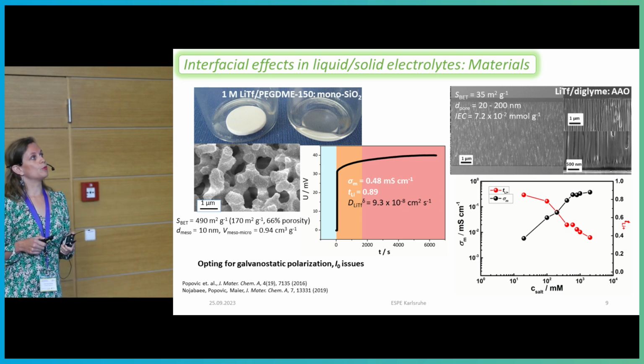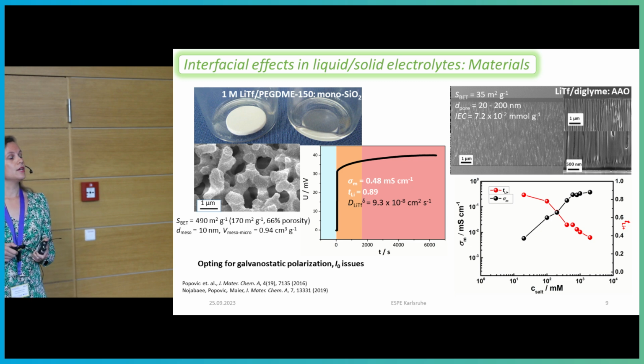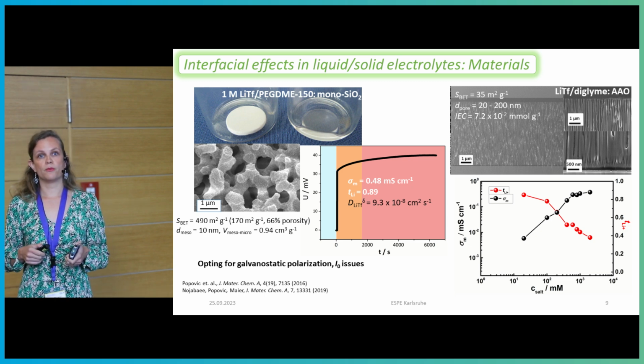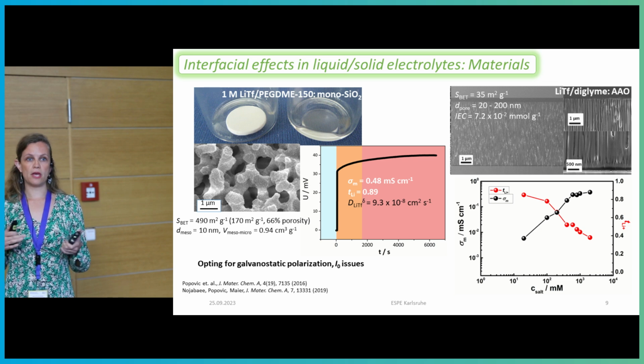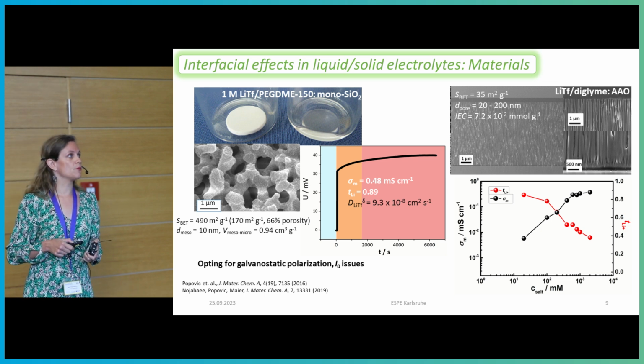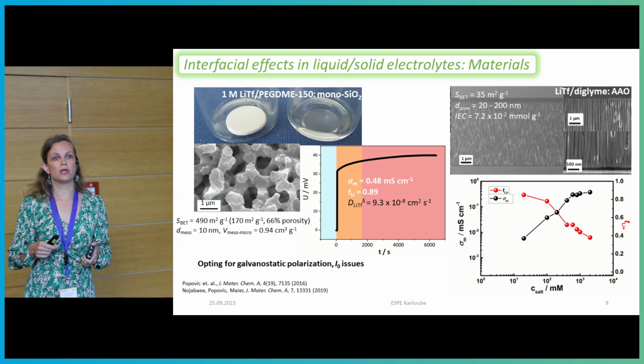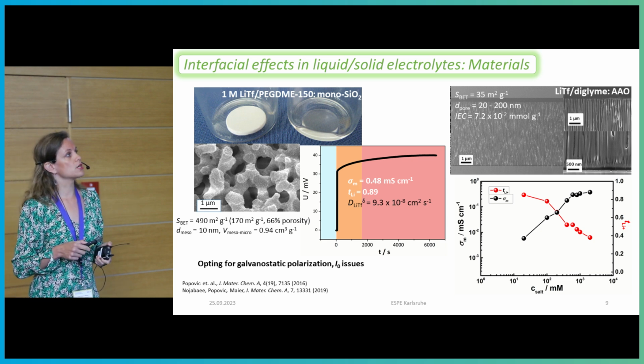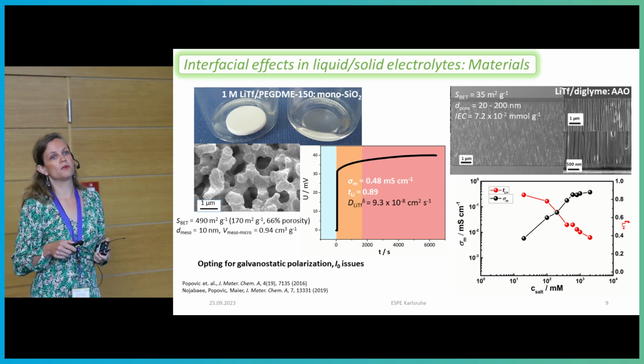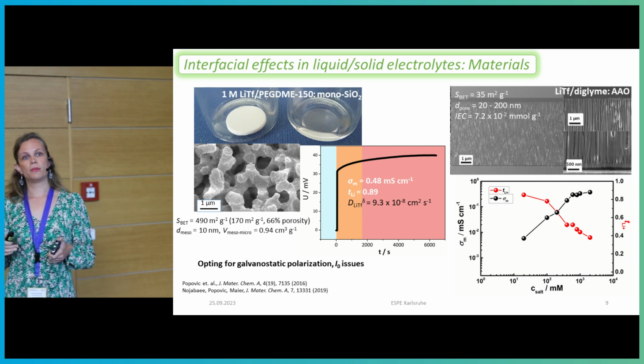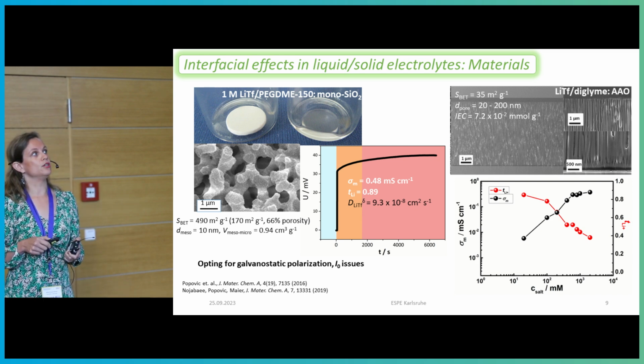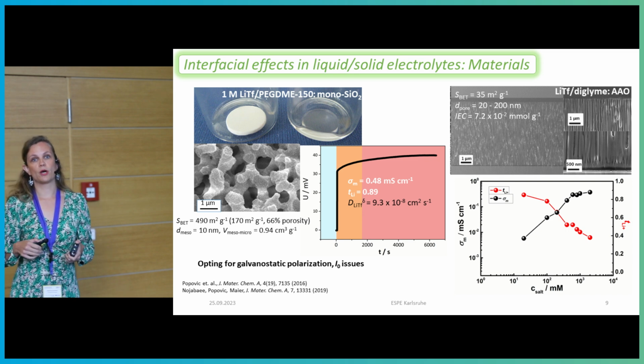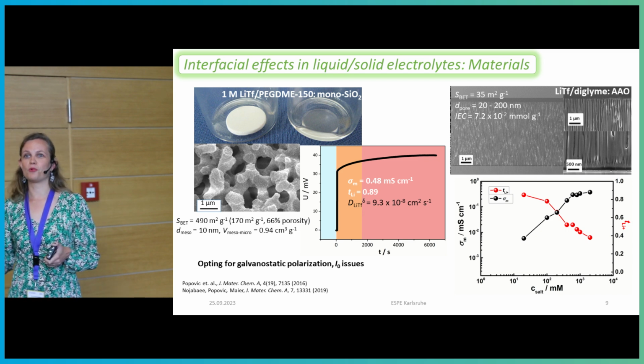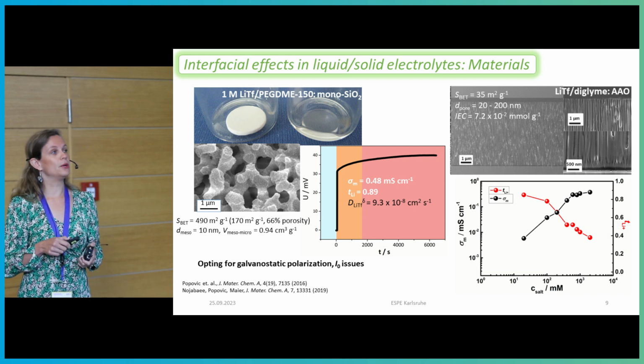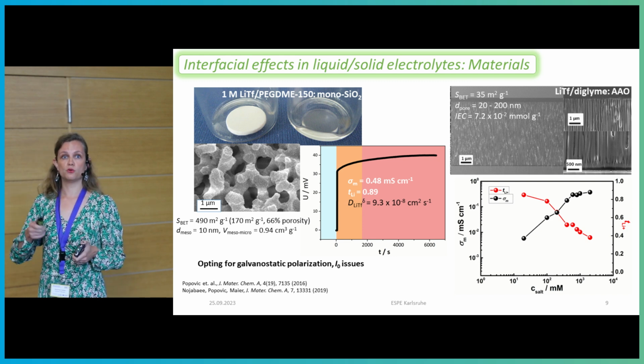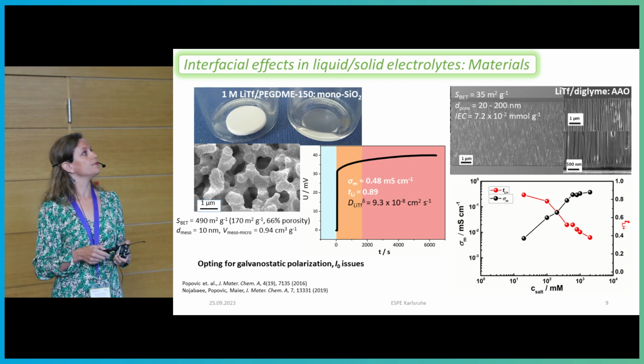What I wanted to stress here is that rather than using a Bruce Vincent method to calculate or measure a transference number, where one has often these initial current issues, we use a galvanostatic polarization method, where we can really both geometrically but also calculate that initial potential. So I would kind of suggest that if you have ever problems with Bruce Vincent's method, please try to invert the situation and just use the galvanostatic polarization method.